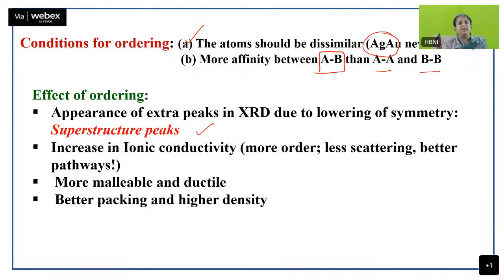Okay, in terms of the properties, what happens? There is an increase in ionic conductivity. We have discussed this when we were talking about the example of pyrochlores and fluorite ionic conductivity, but I can still again talk about it. When you have an ordered material, there is an increase in ionic conductivity. Why? Because when there is an ordering, there is some kind of order in the material. The mobility of the ion, which is carrying the current, faces less scattering. So mobility is higher and hence better pathways. So the ionic conductivity is more in your ordered compound.